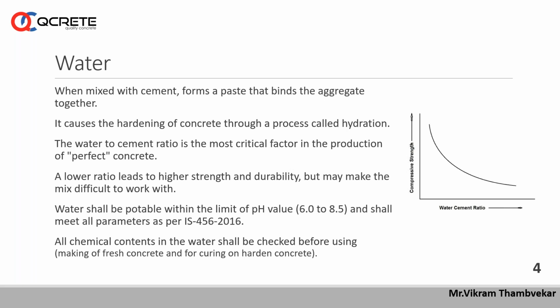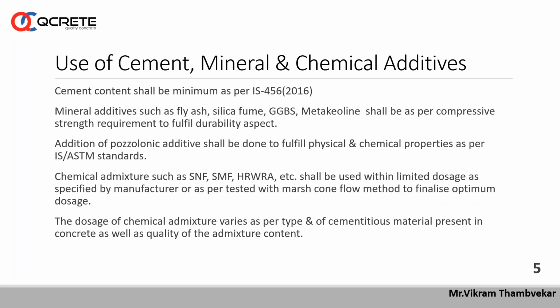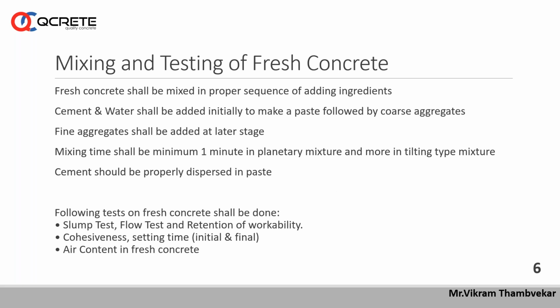If anybody is using curing compound, care shall be taken that all the surface should be moist before applying the curing compound. Then use of cement, minerals, chemical additives, that was already explained very well by Kaushika sir in his last seminar. Whereas I want to say, if the quantity of admixture is not in a proper proportion, then it may give some adverse effect also. So use of chemical admixture should be limited as per specification, and one should test it for its compatibility with the cement which is being used. So this care has to be taken for making fresh concrete.